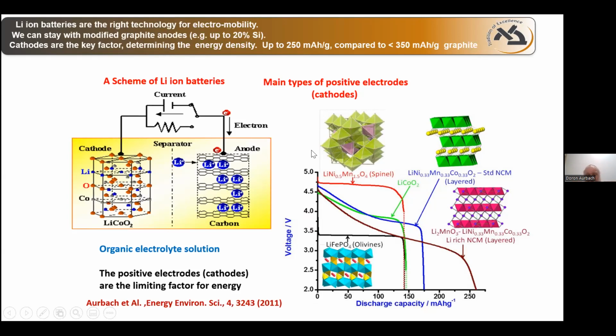So what I show you here are major structures and major presentation of cathodes by voltage as a function of the discharge capacity. We see the voltage profiles of the structures. This is a spinel structure, these are layer structures, this is olivine structure. When we have a layer structure, we have two-dimensional diffusion. Here we have three-dimensional diffusion, and here we have one-dimensional diffusion in the olivine. And the voltage profile really provides a very good hint about the process.